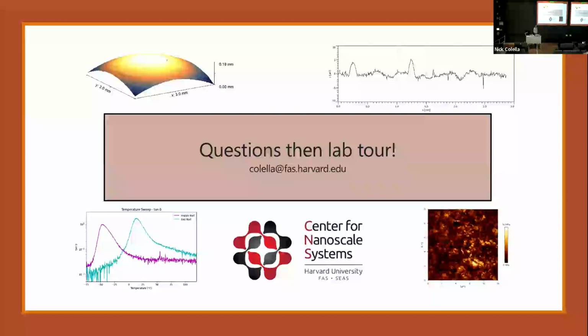Otherwise, it's completely transparent. So completely transparent is okay. Diffracting properties, depending on the thickness, can be an issue. So if we're going to have light that reflects off the substrate and then does some weird diffraction as it comes back up, so typically a very thin film, like 300 nanometers or less, then the AFM is probably a better characterization technique for the surface. If you have a thicker film or just a transparent film that's, again, thicker, then it's perfectly fine. So the transparency is not an issue, it's the diffraction that is.